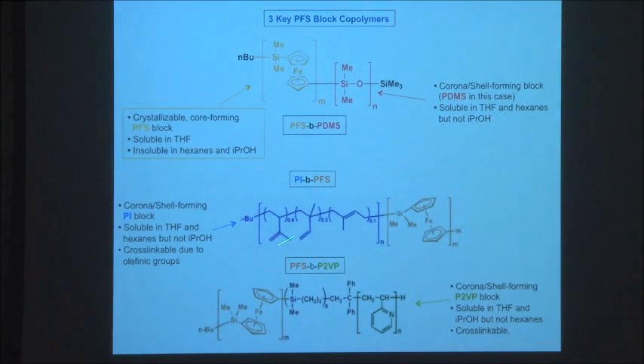So if you put this in hexanes, hexanes is a good solvent for the polyisoprene. It's a poor solvent for the crystallizable dimethyl PFS block. But a key feature of the polyisoprene is you have these vinyl groups present which allow you to do chemistry such as crosslinking, which we'll use later in the talk.